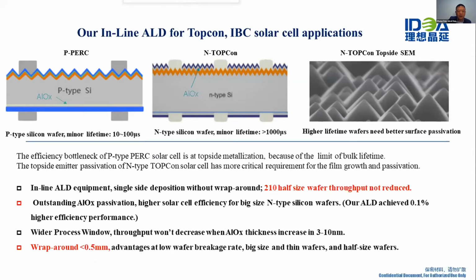And for that, you can see that for the top side emitter, the top side emitter passivation of N-type TOPCon solar cell has more critical requirements for film growth and passivation. And it is very important to be without wraparound. This is very critical for TOPCon solar cells. And our TOPCon customers are very happy with our ALD because we are doing very well without wraparound. And by the way, PERC solar cells mass production also don't like wraparound.